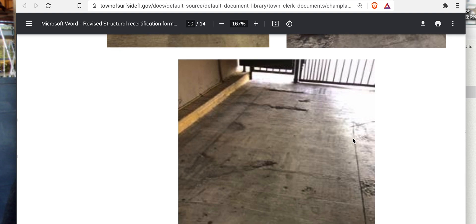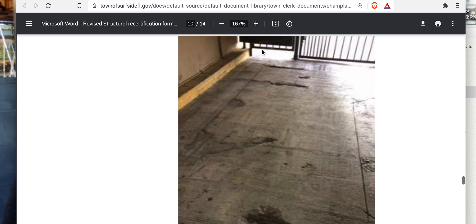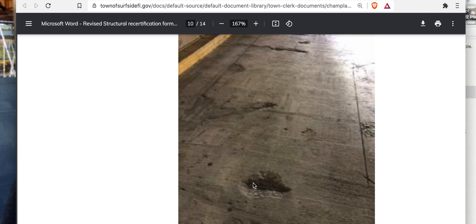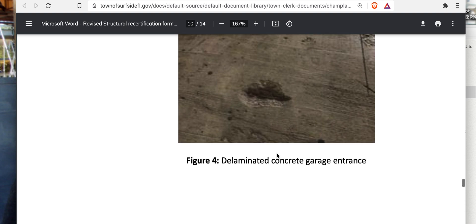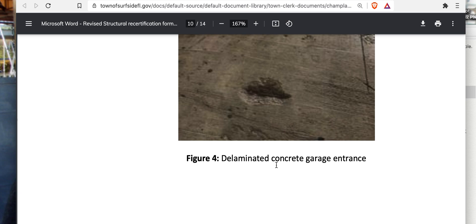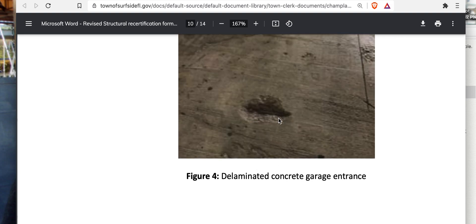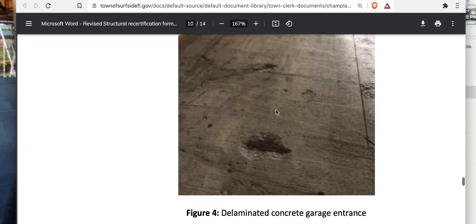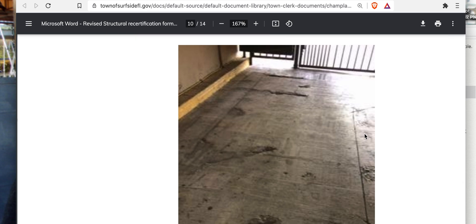The car probably goes across a sensor that opens the gate. This is likely the car entrance and the pedestrian entrance. Now there may be rust jacking going on and the steel is starting to look very questionable. This is a covered area — theoretically less salt exposure — but salts still come from cars. Why is the deterioration concentrated over here and not where cars stop? That's where you'd expect more salt from drips and wiper blades.